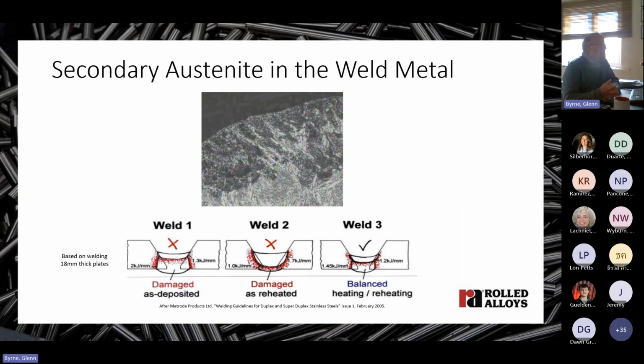Now we talk about secondary austenite in weld metal. We see preferential corrosion of secondary austenite or reformed austenite in welds. Now, the cooling rates in welds are very fast, so a first pass of a weld can be very ferritic because the austenite hasn't had time to fully transform. Subsequent passes cause more austenite to form, but the cooling rates are again still high, and the elements in the steel can't diffuse into their preferred phase quickly enough. So the austenite can be quite lean.